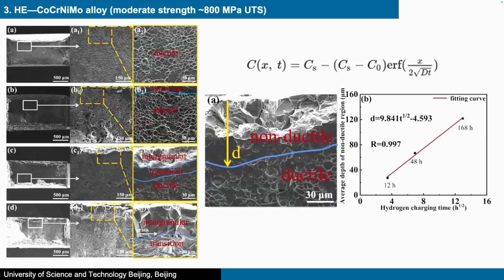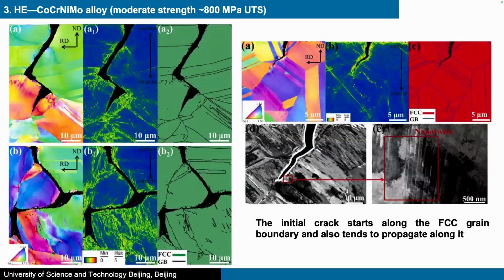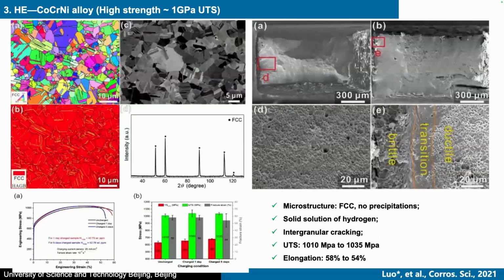This is some of the cracking morphology after the tensile test. And we also found the charging time, which means different concentration, correlates with the cracking depth. And this is the crack inside. We found that the initial crack starts along the FCC grain boundaries and also tends to propagate along the grain boundary. Then we come to the high strength alloy.